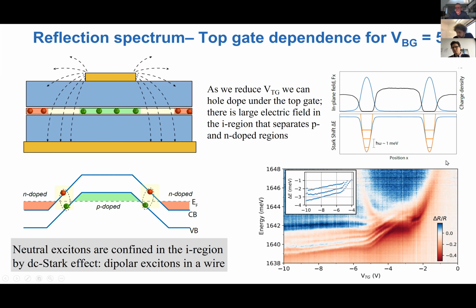As we reduce it, we start to compensate for the electron doping, and therefore reduce the electron doping because of the top gate voltage. So we go back to the exciton level, and as we decrease it further, we see that on the one hand, there is a region where we have the repulsive polaron, but there are additional lines, many discrete lines that are much narrower, about a factor of 10, 20 narrower than the exciton line. And they shift initially abruptly and then slowing down.